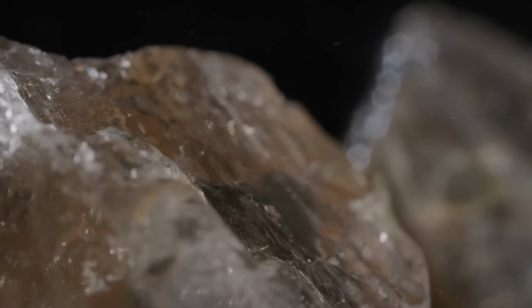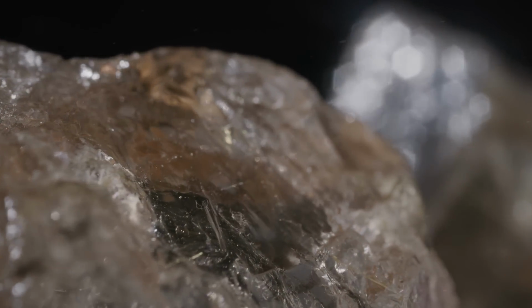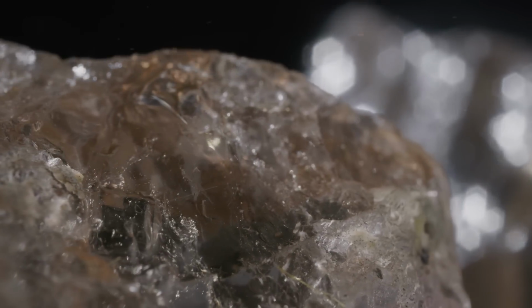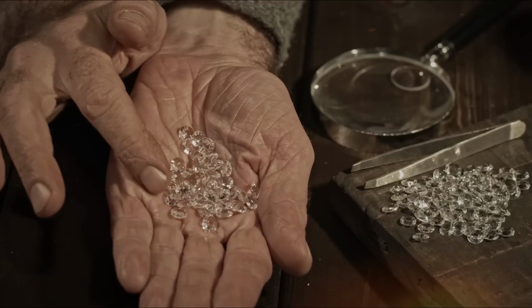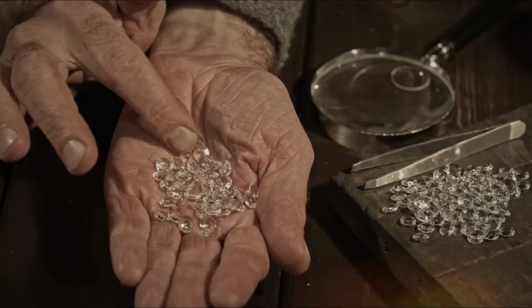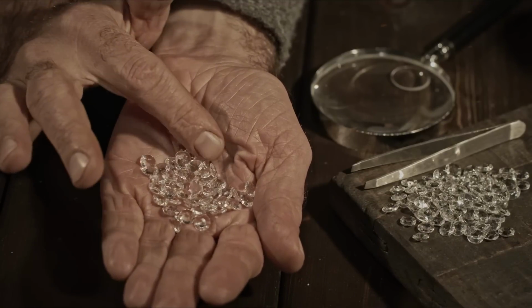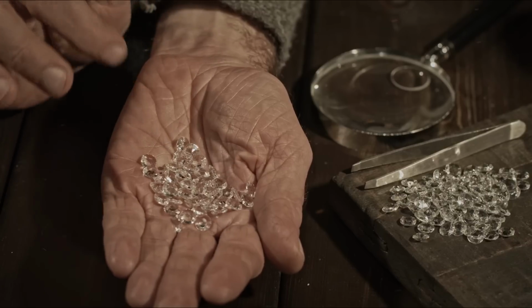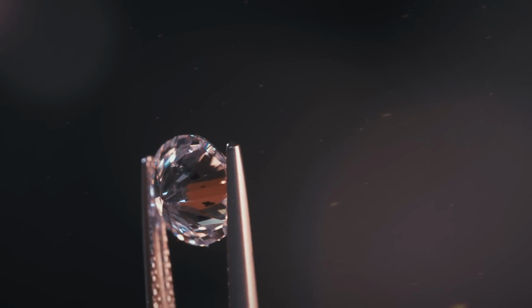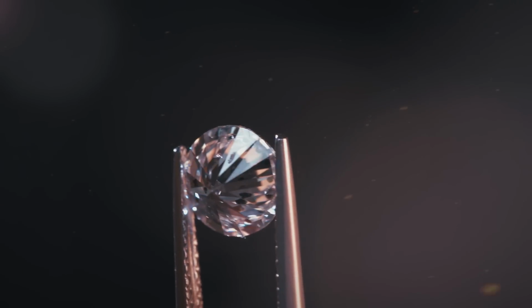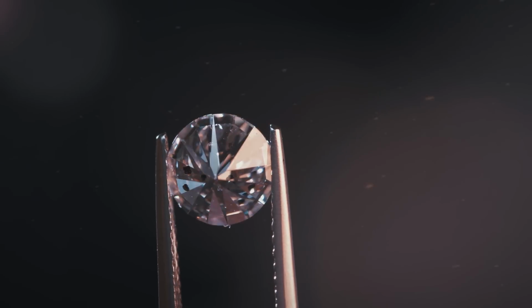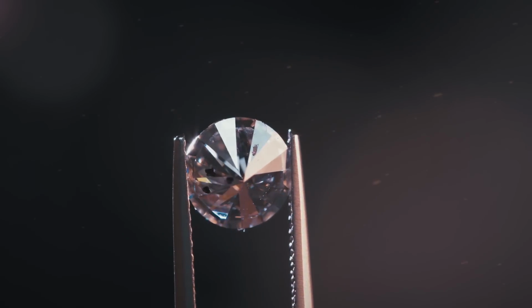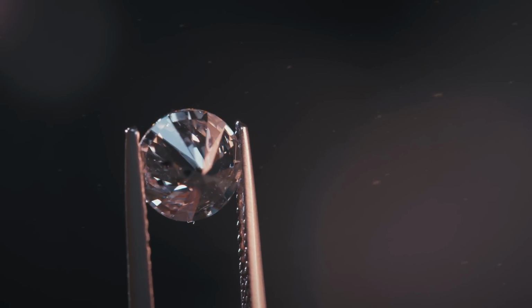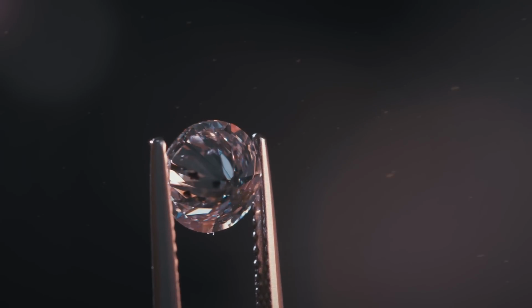Within 5 days, 5 more confirmed specimens were recovered, ranging from 0.7 to 3.1 carats rough, all with heat-reactive coatings that had masked them from traditional screening. The lesson: not all barren ground is empty, and not all debris is worthless. Thermal behavior, when interpreted in context, reveals more than just mineral identity. It can uncover operational blind spots, misclassifications, and marketable assets buried in plain sight.